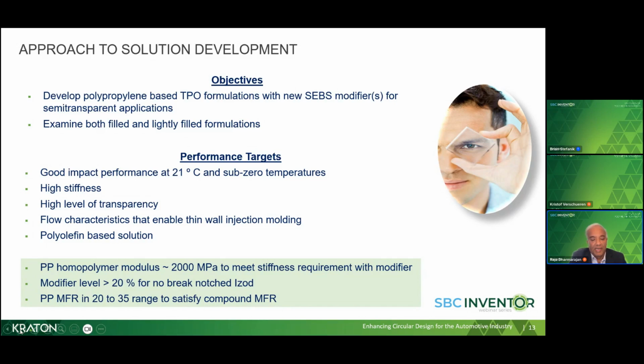So the homopolymer that we selected has a stiffness of 2,000 megapascals, and a flow of 20 MFR, which is in the right range for injection molding application. So before we did our detailed modifier study, we did some benchmarking study to figure out what is the level of modifier that we need in order to achieve high impact strength, both at room temperature and low temperature. So this was a perturbation study where we varied the modifier from 20 to 30%. And we found that we need at least over 20% modifier content to achieve a no-break notched Izod.